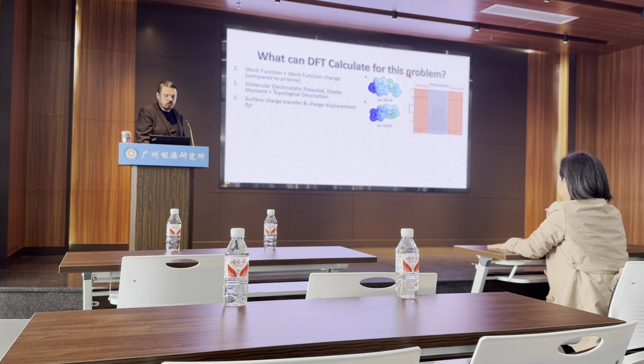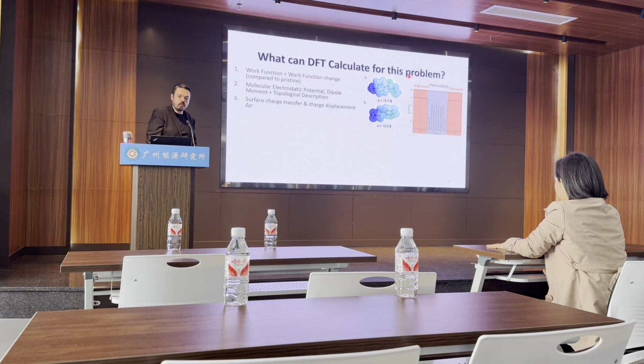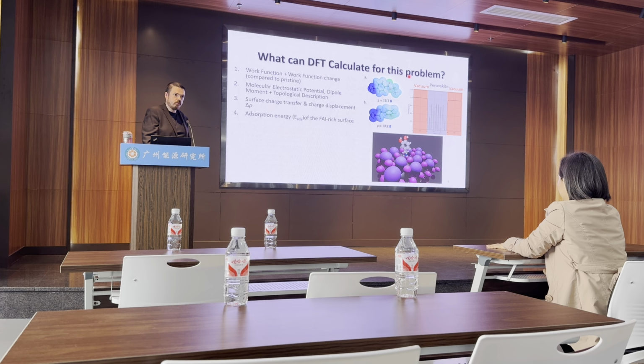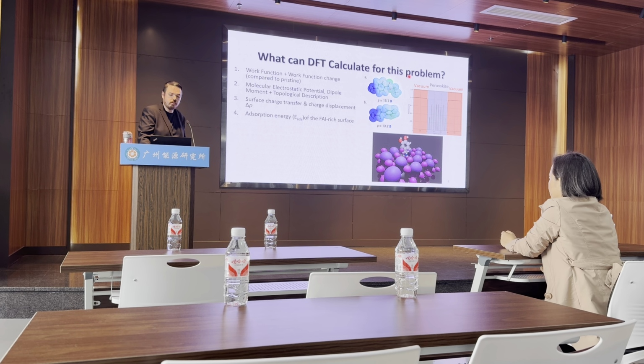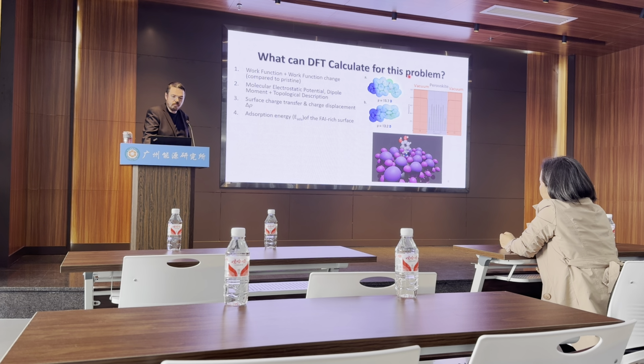We can have surface charge transfer and charge displacement. So the passivator can displace the charge in the perovskite, basically induce the dipole. Adsorption energy of the formamidinium iodide-rich surface, we mostly consider formamidinium lead iodide. So basically in the experiment they're slightly mixed, but in theory we just consider the pure case, so the alpha phase, the black phase. And finally, we can also do the PbI2-rich surface.